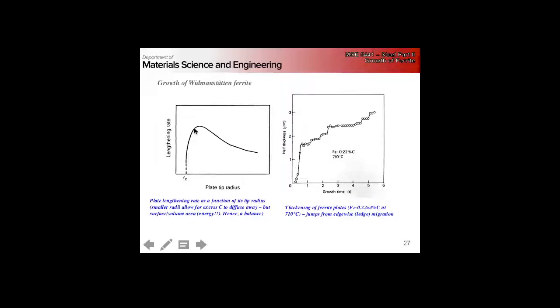Why does a smaller, thinner needle grow faster than a wider one? Higher energy, but how so? Remember, we've got partitioning going on, so the smaller the tip, the easier excess carbon can diffuse away from it. We're not pushing as big of a diffusion field out in front.